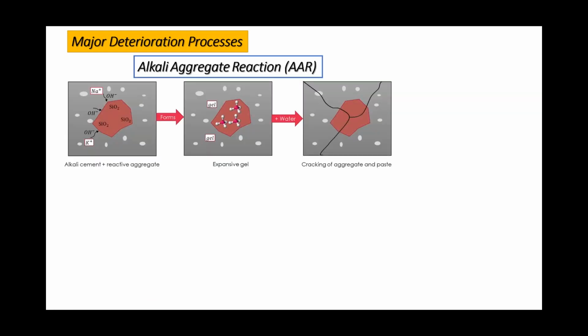So first, I'll start with the alkali aggregate reaction. When aggregates containing certain forms of silica react with alkali hydroxide inside the concrete, they form a gel, and this gel swells as it absorbs water from the surrounding cement paste or the environment. These gels later on can induce enough expansive pressure on our concrete surface, which eventually leads to cracking inside the concrete, which is not a good item at all for the durability.